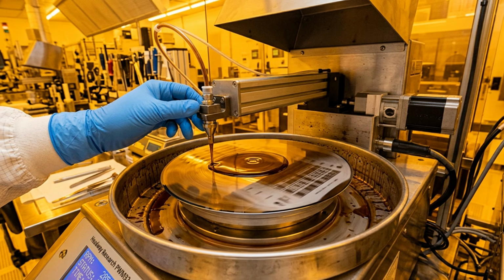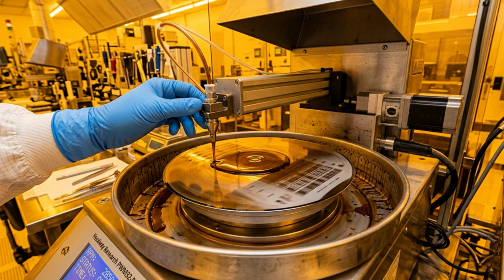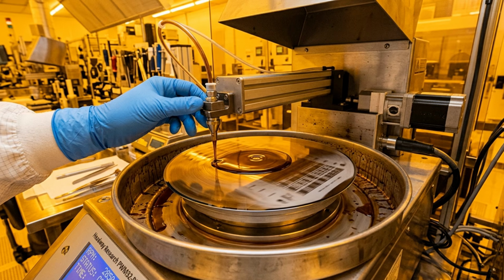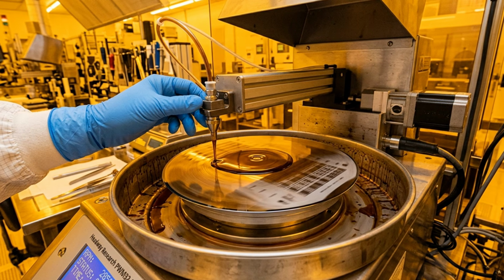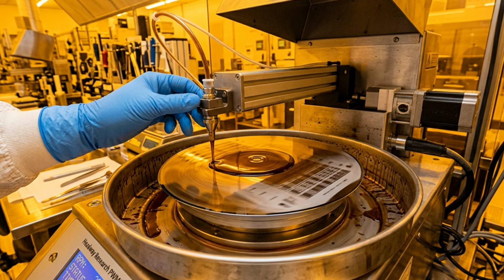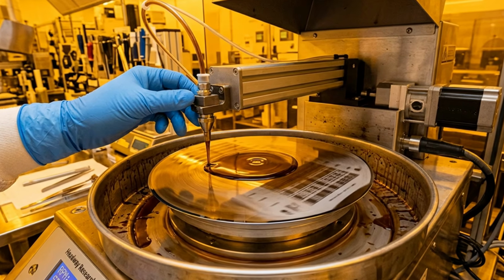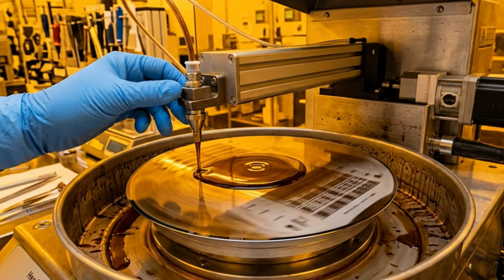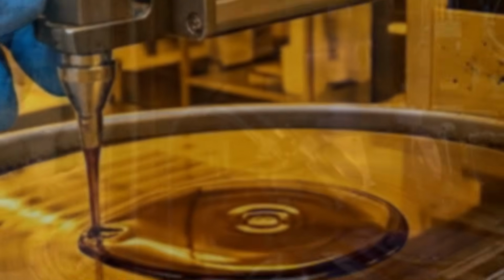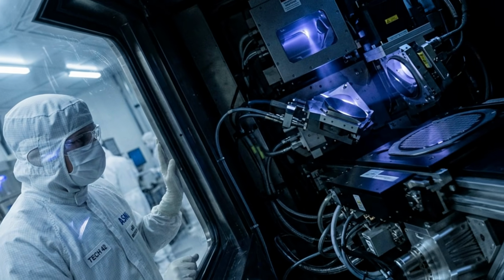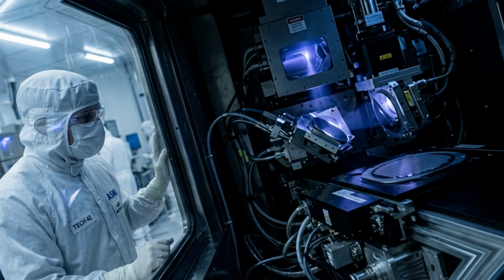Then the process repeats, and repeats. And repeats again. For NVIDIA's most advanced chips, this process happens over 150 times. Each layer is aligned to the ones below it with a precision of less than 5 nanometers. And this is where things get truly extraordinary.